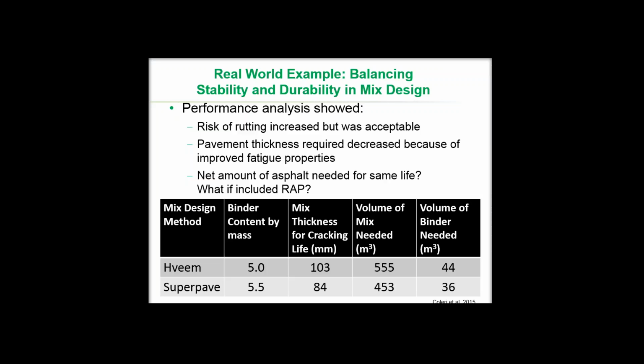There are a number of examples that were run, but for an example pavement, from 4 inches or 103 millimeters to about 3 and a quarter inches, about 84 millimeters. So about an 18% reduction in the thickness. What this does is overall reduces the amount of mix needed, and even though we increased the binder content, the amount of total binder needed was reduced from 44 cubic meters to 36 cubic meters. So this is the kind of analysis where you may get a result that you were not necessarily looking for.